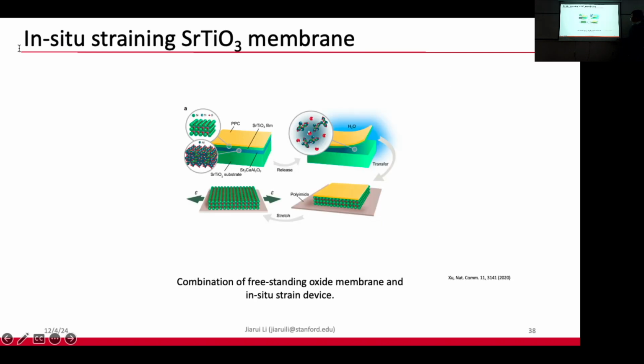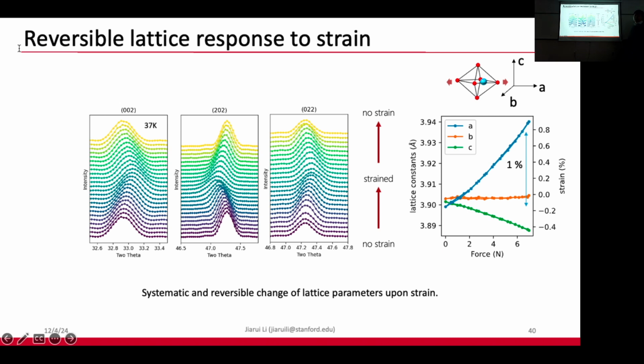So this is our methodology. When we apply strain, we characterize their lattice constant through diffraction. So we measure multiple Bragg peaks, and through refinement. When you look at this, the Bragg peak moves back and forth as we apply and release the strain, as we stretch the material and we release it. So you see that the Bragg peak position moves back and forth. Correspondingly, the lattice constant gets stretched up and released back. So through refinement, we know that the A lattice constant gets stretched by more than 1%, and it is reversible.